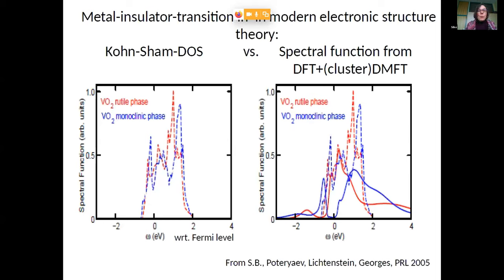So I have shown you the band structure before, and on the left side here is just the density of states corresponding to those band structures. The dashed blue and red lines here are just DFT, LDA densities of states corresponding to the bands that I have shown you before. What you see in the T2G manifold is that, if anything, the bandwidth is slightly smaller in the rutile phase, which is the metallic one, than in the insulating one. That already tells you that it's probably not just a plain vanilla Hubbard model-like metal-insulator transition in terms of bandwidths and Coulomb interactions. So there's something more interesting going on.